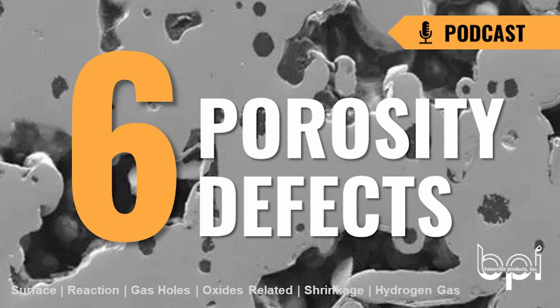It's a progression as you start to feed through the risers, depending on how well you did it. Like you said, the elongated shrinkage is your first near miss. Then it goes to the sponge shrinkage, which means you've missed your feeding range by just a little bit more. And then the one where you just don't quite have it yet goes to a shrinkage cavity. So it's a progression of shrinkage defects, with elongated the least severe, then sponge shrinkage, and then the shrinkage cavity.